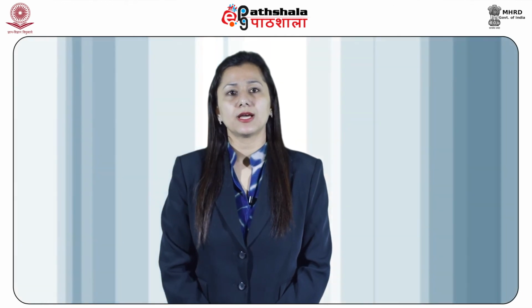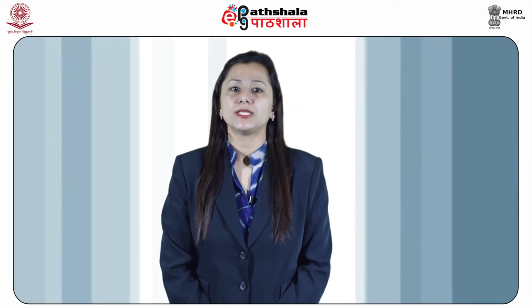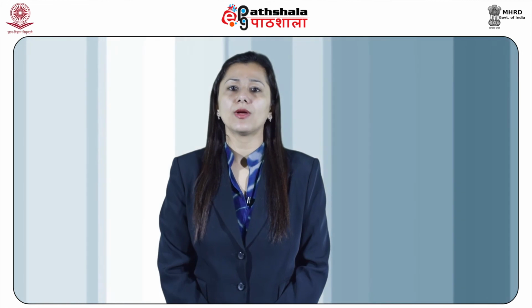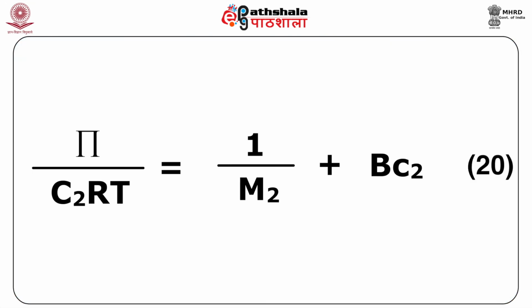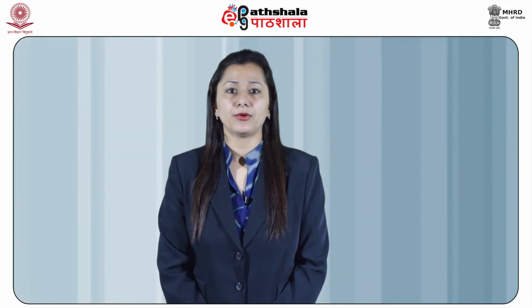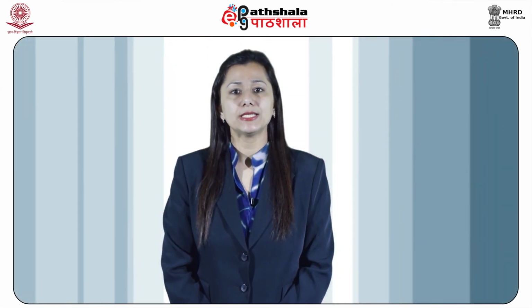The higher terms are insignificant. Thus, retaining only the first two terms on the right hand side, we get pi upon C2 RT equals to 1 by M2 plus B times C2, as our equation 20. Equation 20 predicts that for a non-ideal solution, the plot of pi upon C2 RT and C2 is linear.